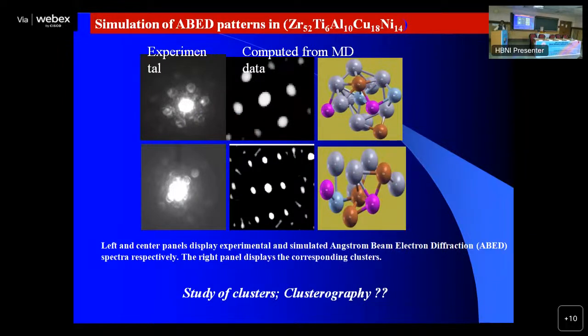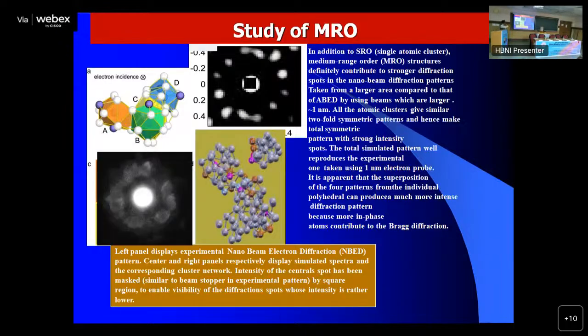So how do they join up? They can join these two clusters with edges coming together, vertices coming together, or sides coming together. This is how two polyhedra can come together. Either the vertices come together, the edges come together, or sides come together. And that information, again, you can ascertain by angstrom beam diffraction. By making the beam a little larger, you get a diffraction pattern from two clusters side by side, and you decipher that, and you will know how the two clusters are joined.